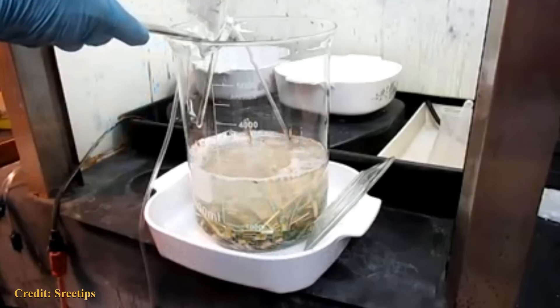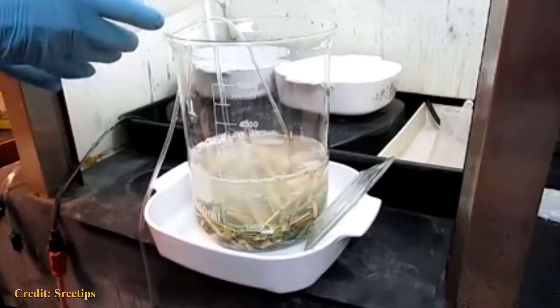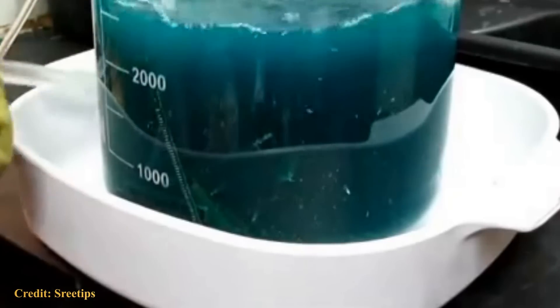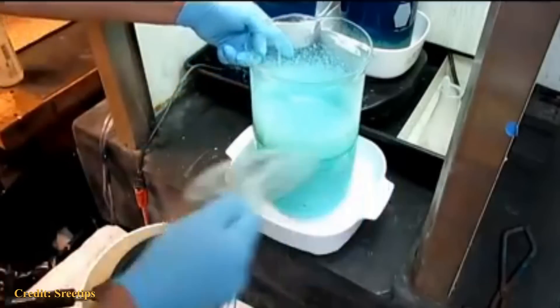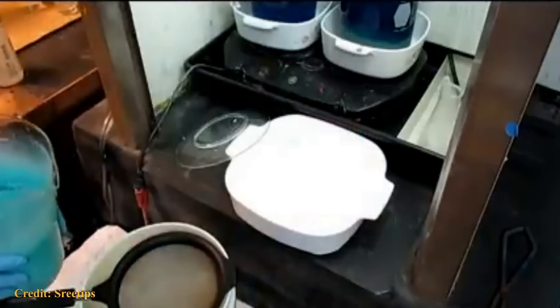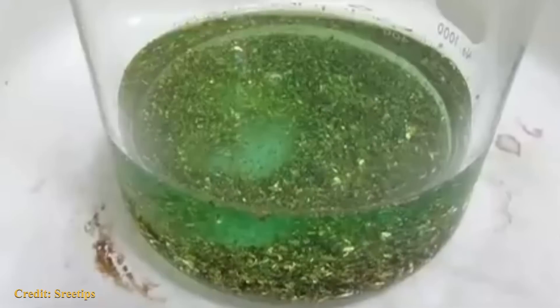There's already a pretty good method for that, which involves chopping up the circuit boards and putting them in a solution of vinegar, hydrogen peroxide, and ordinary table salt. What that does is attack the copper, tin, and solder holding the gold on top of the circuit board — it eats those away, which is why the solution goes blue, and the gold flakes float off, leaving you with scrap boards and a blue sludge. You wash that and collect the gold, then dissolve the gold in household bleach.